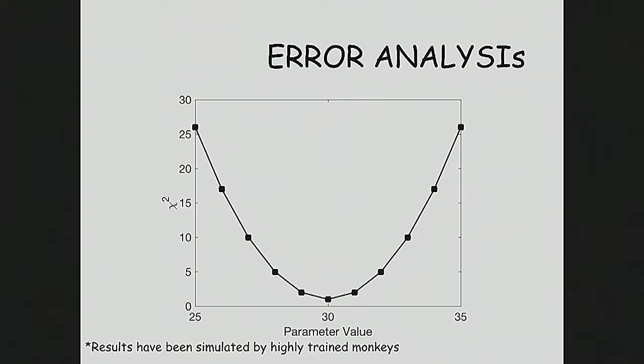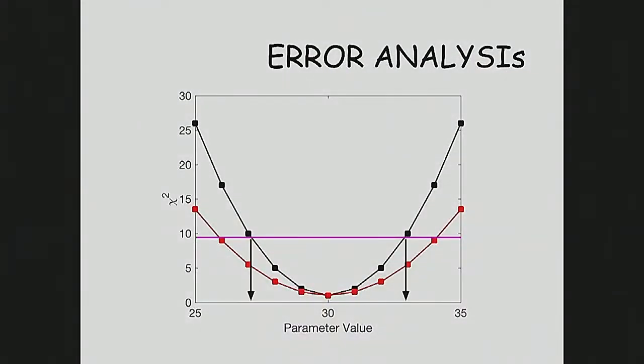So for a given model, you look at the number of degrees of freedom of that model. You can do a statistical test and basically get a confidence interval on your chi-squared. So graphically, you have some multiplication factor, and then where this factor intersects your chi-squared distribution, you get the confidence interval on whatever parameter you're looking at. So illustrated here would be two different models and a given chi-squared confidence interval and the resulting error bars in each.